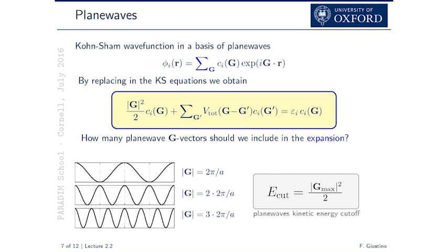So ideally, one wants a mathematically exact expression where you have all the terms in the expansion, but that is numerically impossible. You may be running calculations for years. But really what you want, suppose you calculate the total energy, for most applications, if you have 3-4 digits accuracy, that's more than enough. So if you achieve a cutoff, suppose 20 or 30 Rydbergs in this number, which gives you a number which is converged to 4 digits, you don't need to go beyond that, because you already achieved your accuracy criterion.